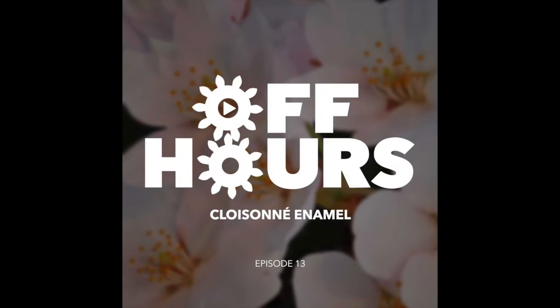So that was my first introduction of that, seeing pieces in the British Museum and the V&A. My real interest as an artist in using enamel came from trying to replicate the Fabergé work that I was seeing. So the first part of that was to do the engraving, the guilloché work underneath. But then the real beauty of the work that Fabergé was doing was taking that guilloché and then covering it with translucent enamel so that the light can shine through the colored glass, hit the engraving work, and between the index of refraction of the glass and the change of direction from the engraving, the bright polished engraving, you get fabulous moire effects and colors coming out of the enamel thanks to the combination of the two.